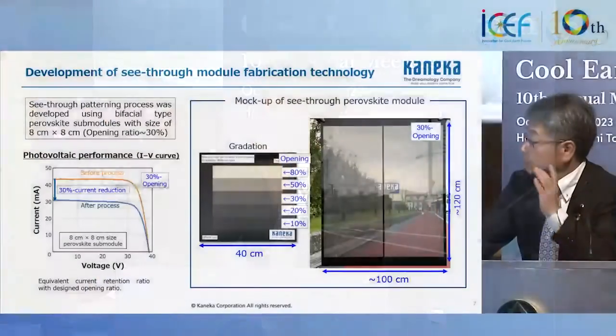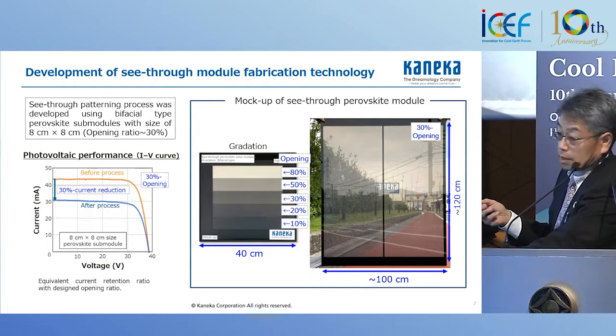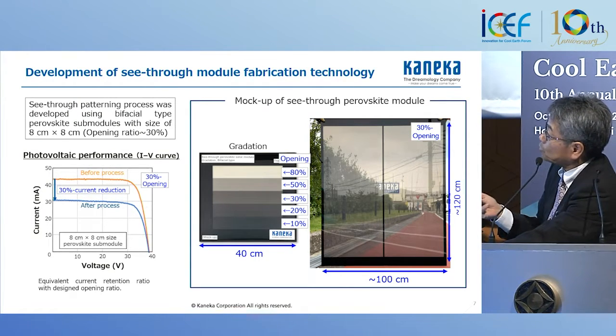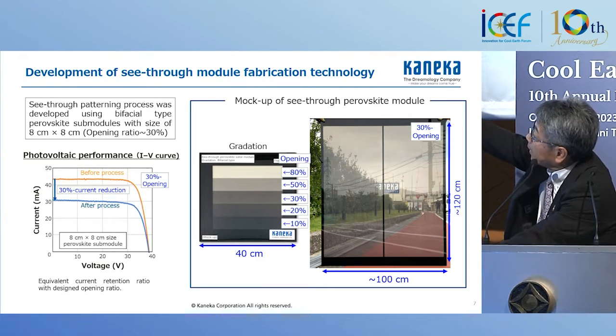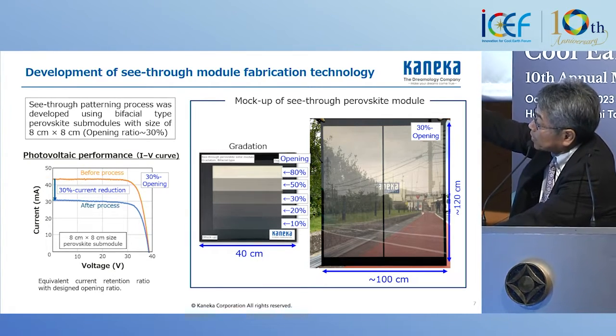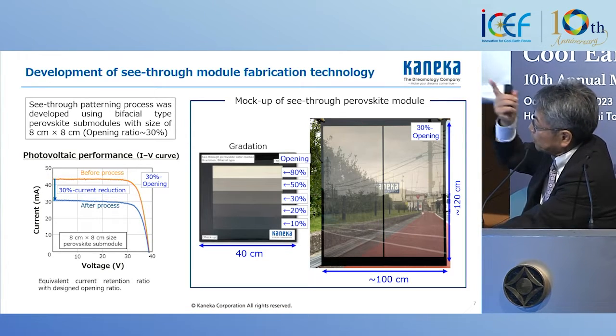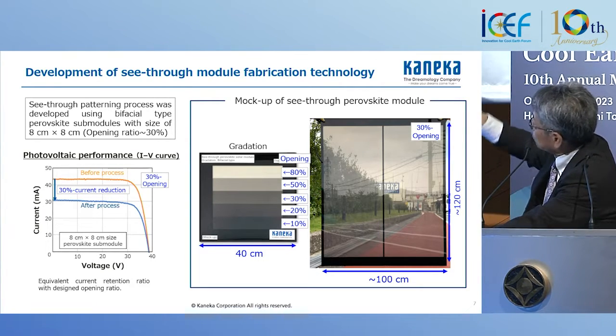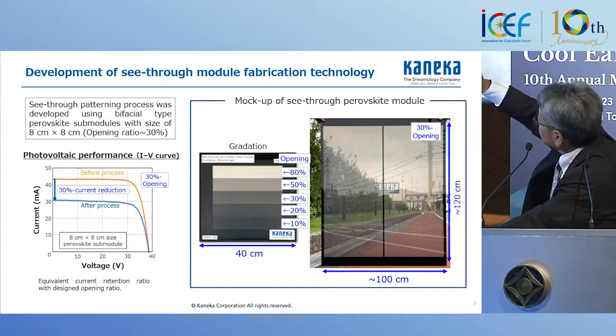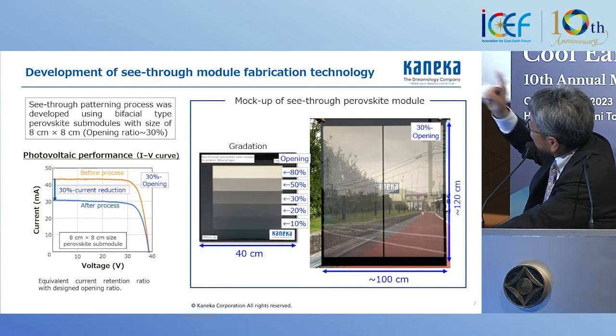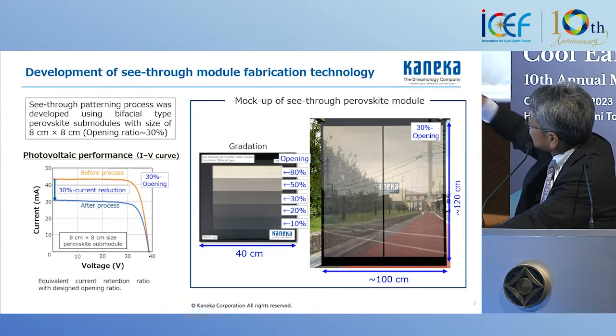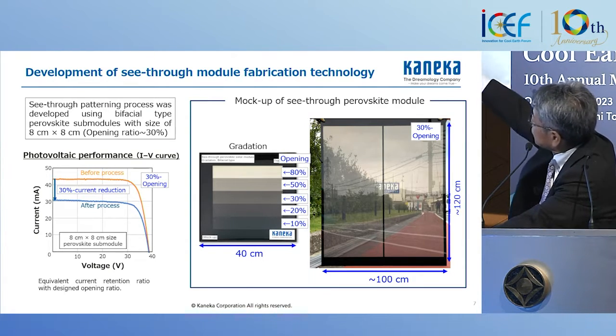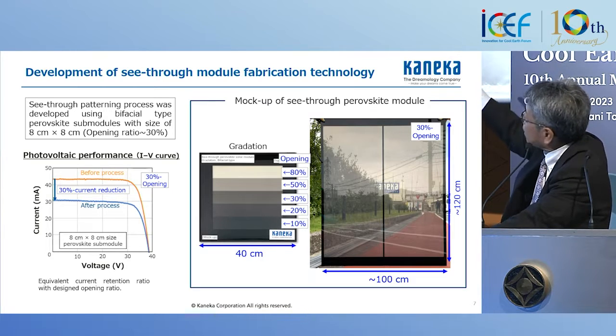Probably you can see my face. So, for making a see-through module, the original is the yellow one, and then we remove 30% to make the opening. This is a case of a 1.2 by 1.0 mock-up of the see-through. You can see that this is bifacial, and from the front side to the rear side, you can see the background of the picture.